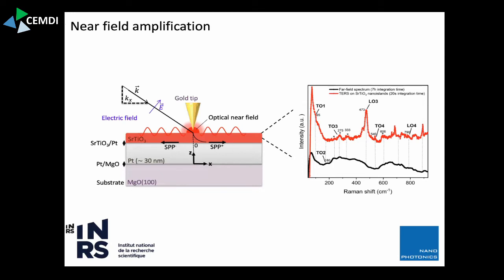And this is, again, the spectrum of the far field of the film. Now, it took 7 hours to integrate to get this picture. Why? Because it's an optically transparent film, which is only 50 nanometers or so thick. There is not a lot of material that gives you optical scattering. So that's already a pain in the neck to get a signature from that one. When we bring the tip into proximity, we get this optical near field effect. And within 20 seconds integration time, we get this optical spectrum.